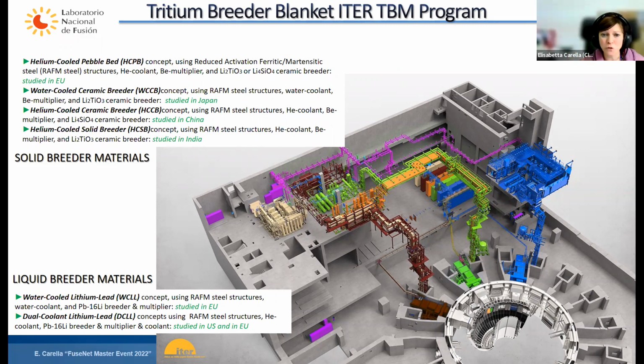So for this reason, and also because it is quite difficult to have a loop working with lead lithium in dynamic conditions, the big quantity of experiments, and there are not so many in Europe, that work with lead lithium are based on lithium in stagnant conditions. There was one in KIT, but it has been stopped with this time life, because, as you can imagine, lead lithium is really corrosive, and the experiments have a really short lifetime. And for this reason, we have built a new facility in CIEMAT to supply materials and experiments to all the EUROfusion colleagues who want to check their materials in dynamic conditions with really extreme conditions, because